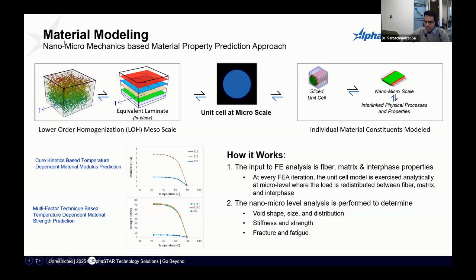To go into more detail on material modeling for chopped fiber filled systems, we use a nano micromechanics based approach where we generate equivalent laminate properties for the given orientation at every element. And this then is dehomogenized all the way down to the nano micro scale. So at every iteration of an FEA model, we can predict the stresses at the constituent level. So then we can predict all damage at the micro level. So we redistribute the load between fiber, matrix, and also the interface. So we consider all these effects, which then feed into our macro scale prediction.